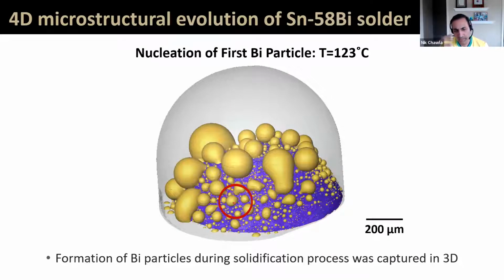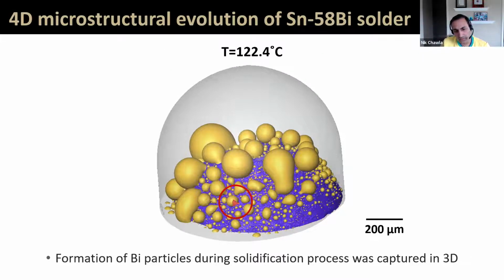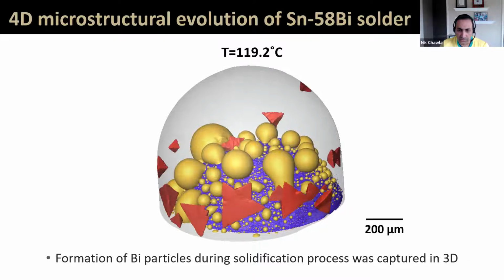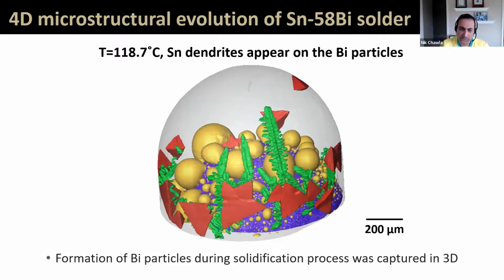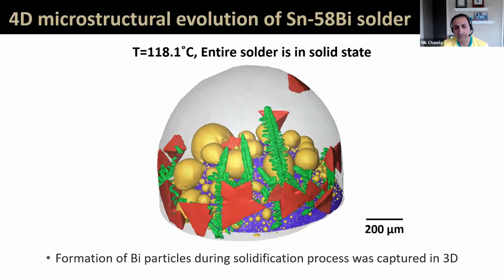Okay, so here's actually a 4D data set. You can pay attention here to this little red dot, which is the initiation of a bismuth particle as the temperature is decreasing. And so you see that start to be a pyramid. That pyramid continues to grow. You have this little guy here, which is a neighboring particle, is also growing. And as that particle grows, they end up joining together. And you see this very nice evolution of the bismuth particles. And then, of course, tin dendrites grow.